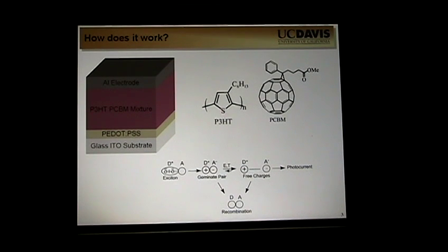So, how does it work? When I'm talking about organics, I'm talking about some conjugated polymer and usually a fullerene — they make a donor-acceptor pair. The idea is you can shine light on this donor-acceptor pair; typically the polymer absorbs more effectively. When the light is absorbed, it very efficiently forms an exciton excited state. This excited state can be separated at the junction between donor materials and acceptor materials. Basically, if this exciton is close enough to this PCBM fullerene, you get a charge separation. This is a very fast process — it happens in less than 100 femtoseconds — and it's a very efficient process.